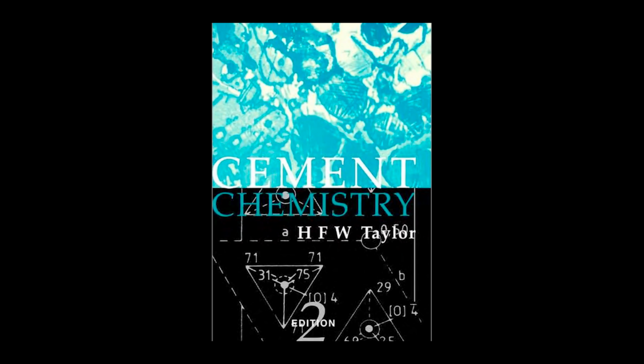Right. First, you have the physical barrier theory. The very rapid initial reaction, which happens within minutes of mixing, deposits a semi-protective, ultra-thin layer, we call it product B, on the surface of the C3S grain. And now think of that. It's only about 1 nanometer thick, but it's non-uniform, and it's dense enough to significantly isolate the C3S from the bulk water solution, which slows the ion exchange down dramatically. So the cement grain essentially seals itself off, but not perfectly.